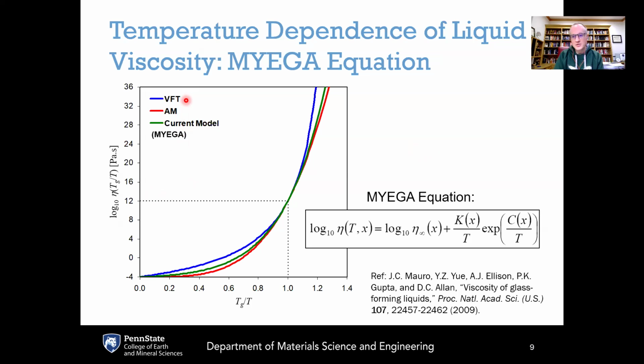It's not a physically derived equation, and it has what's called a mathematical singularity, meaning that it actually predicts viscosity going to infinity at a finite temperature, which is unphysical. And the reason that this is important for our cathedral glass question is that we're interested in the flow of glass at very low temperatures, and the VFT equation gives highly inaccurate results in low temperatures, including this prediction of an infinite viscosity at a finite temperature.